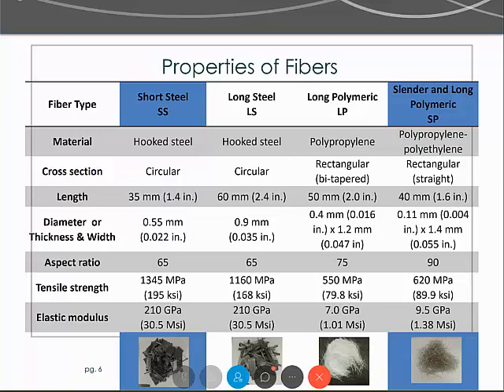Within the steel ones, we wanted to keep them very similar. So they're actually the same manufacturer of steel fibers. They're the same aspect ratio. So that means the length to diameter ratio is the same. But we wanted to pick a longer one and a shorter one, because in the research they've shown in the past, when people have been studying these for several years, that changing the aspect ratio can change the performance. Having longer fibers in general have been reported to be more beneficial at arresting cracks. So we wanted to kind of see if we could capture that as well and see how much that affected. Again, the end goal is to see how much it affects that residual strength ratio property that we use in the design of fiber reinforced concrete pavements.